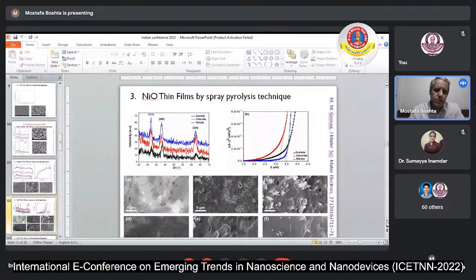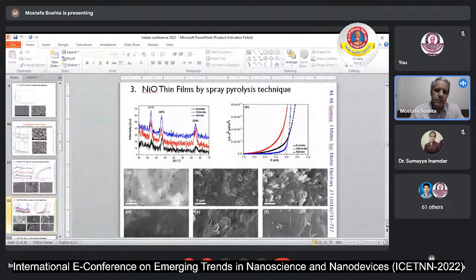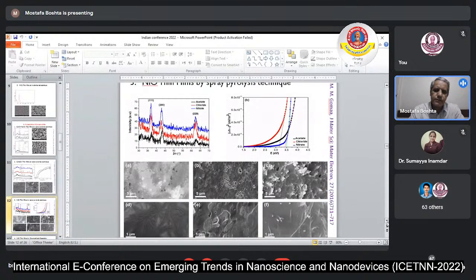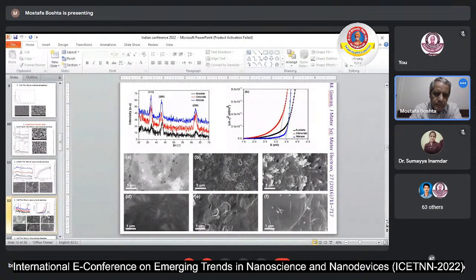Also, as we know, nickel oxide is one of the important materials. There are a lot of applications because it has a lot of advantages. We deposit the nickel oxide by spray pyrolysis through three different sources for the nickel material: acetate, chloride, and nitrate. So we deposit these three source materials, and we found that we have a different quality of the thin film from X-ray and also from scanning electron microscope. We have a different surface structure built from these three different sources. And also the energy band gap differs a little bit according to the source of the material which we used in the spray as a starting material.